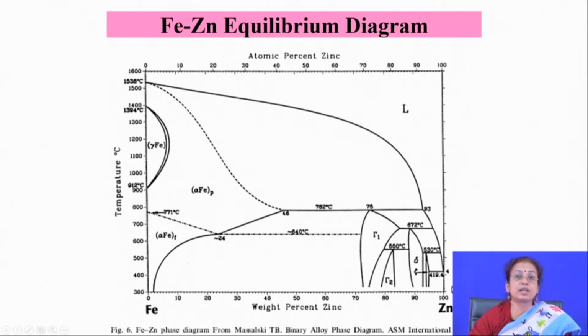So, you have to see the phase diagram from the zinc rich side. From the iron rich side there are different intermetallics which might form, like gamma 1, gamma 2, then delta phase, zeta phase, and then pure zinc onto the top with iron in solution. These are the different intermetallics which can form at the interface, starting from the interface. Most of these intermetallics are very brittle in nature.